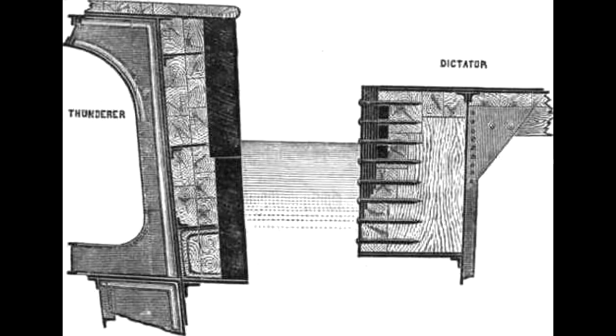which can punch through your armor, but there's also a ton of other shell firing guns, smaller cannon, anti-personnel weapons, etc., those are still substantially going to be stopped by your armor belt, which means that your ship is going to be in a much better condition than if that whole armor section had just shattered, failed, and fallen off, at which point, obviously, then all that other fire could get in easily.